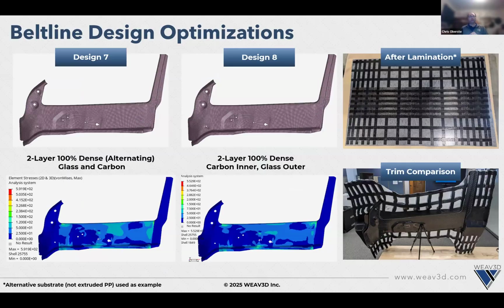So flipping briefly over to the beltline stiffener itself, we ended up going through a number of design iterations here. We came up with 2 different designs that actually have the same amount of glass and carbon fiber in them, but that glass and carbon fiber is structured differently. So in design 7 that you see on the left, the lattice is produced with a striping effect of glass and carbon fiber above and below each other. And you can actually see this in that graphic that I've put on the right here with the lamination image. So you can see there's 2 different colors of black. The more matte black color is the carbon fiber reinforced tape, and the darker black color is the glass fiber reinforced tape with a black polypropylene.